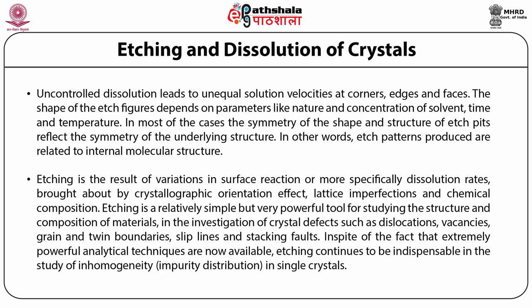Etching is the result of variations in surface reaction or more specifically dissolution rates brought about by crystallographic orientation effect, lattice imperfections and chemical composition. Etching is a relatively simple but very powerful tool for studying the structure and composition of materials in the investigation of crystal defects such as dislocations, vacancies, grain and twin boundaries, slip lines and stacking faults. In spite of the fact that extremely powerful analytical techniques are now available, crystal etching continues to be indispensable in the study of inhomogeneity, that is impurity distribution in single crystals.